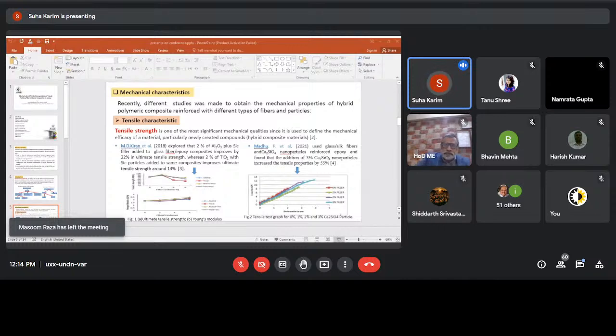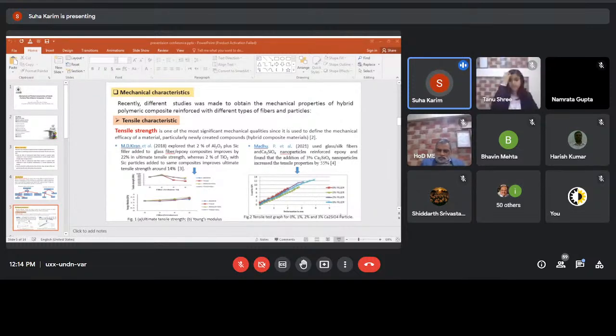Related to the mechanical characterizations, the most significant characterization is the tensile property. Tensile properties are one of the most significant mechanical properties, and that's why many researchers are interested in studying this property. Karen in 2018 found that 2% of aluminum plus silicon carbide particles with glass fiber in epoxy composites improved the ultimate tensile strength by about 22%, whereas 2% of titanium oxide with silicon carbide particles improved the ultimate tensile strength by around 14%. As we see from figure one, the effect of different types of particles with the glass fiber and epoxy composites on the ultimate tensile strength and Young's modulus.